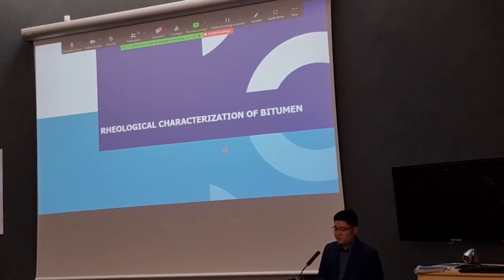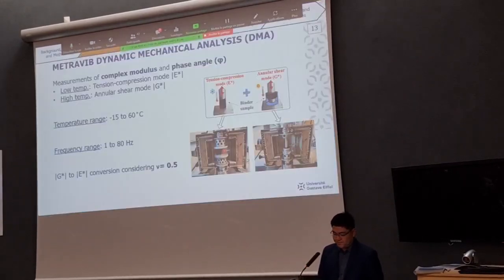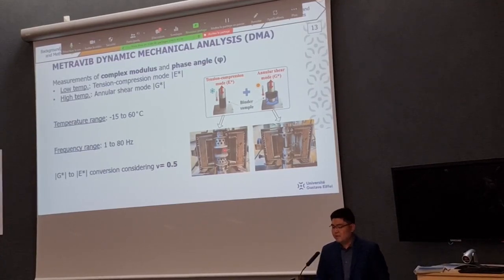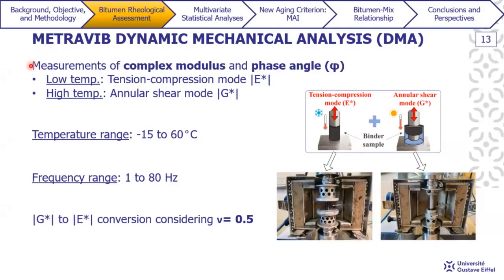So now let's move on to the rheological characterization of our bitumen samples. So in this case, a frequency sweep test at multiple temperatures was conducted via Metravib dynamic mechanical analysis. And bitumen's complex modulus and phase angle were measured in tension compression mode at low temperature, and at high temperature in annular shear mode. The testing temperature range was from minus 15 to 60 degrees Celsius, whereas the frequency range was from 1 to 80 hertz.